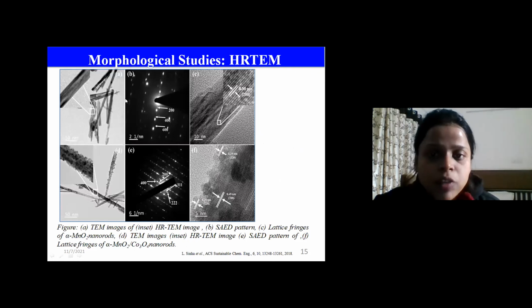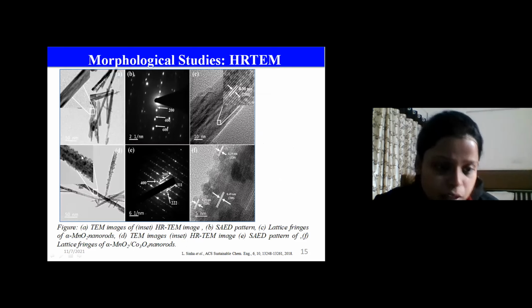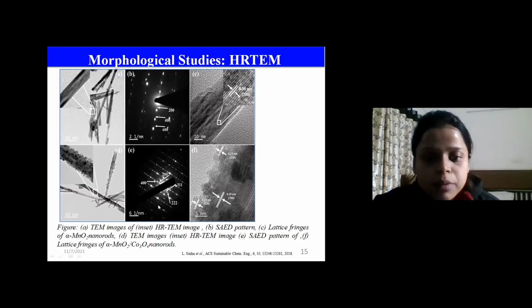This is the morphological study of the hybrid nanomaterial and MnO2 nanorods. So this is the HRTEM image of the MnO2 nanorods, and these are for the hybrid nanomaterial. And here we can see that the Co3O4 nanoparticles have been deposited over the alpha MnO2 nanorods, and these are the SAED pattern and lattice fringes, which confirm the structural parameters of the hybrid nanomaterial and MnO2 nanorods.